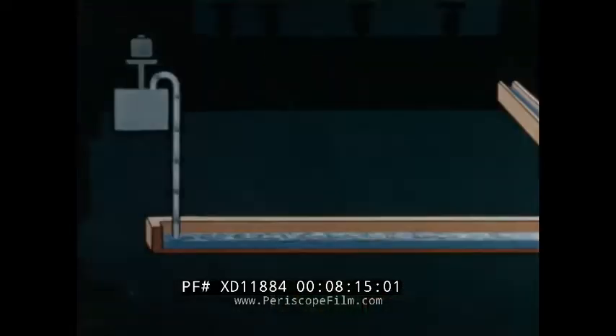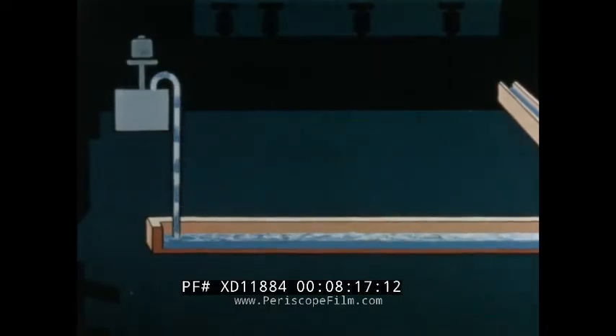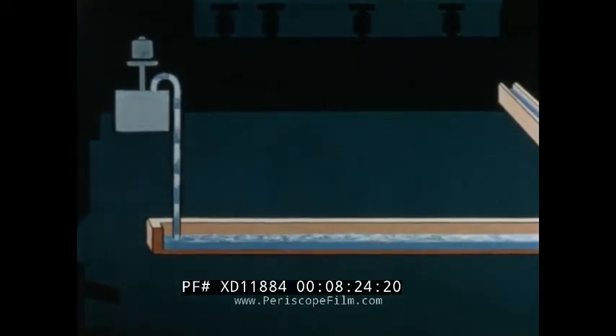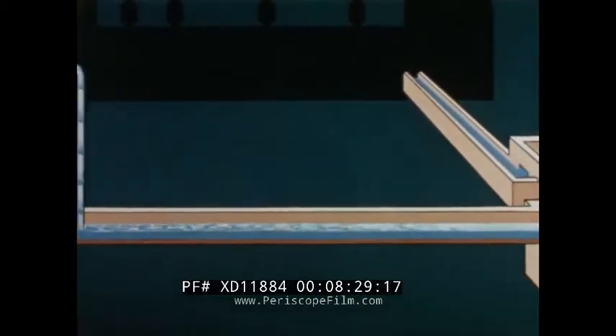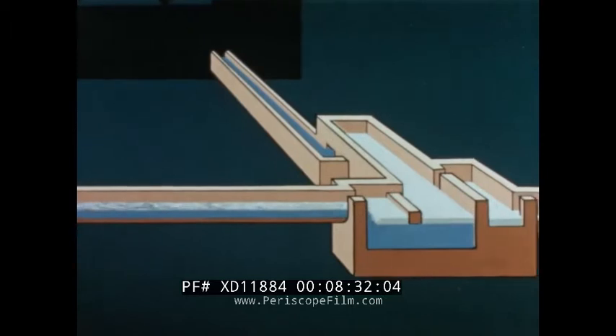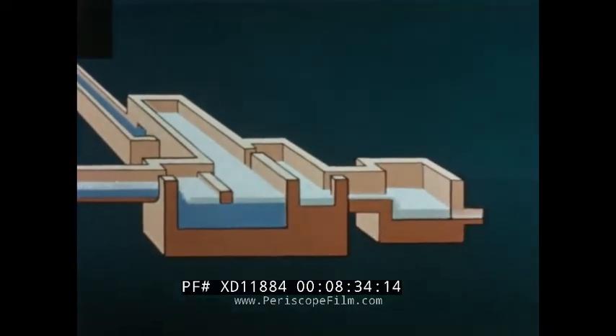Zinc not dissolved by the lead droplets and the furnace gases leave the condenser and pass to a water scrubbing system. There, the last traces of zinc and lead are recovered in the form of blue powder. The cleaned furnace gases are then available for preheating the coke and the air used in the process. Back in the condenser, the solution of molten zinc and lead is pumped into a water-cooled launder. The cooling separates the molten metals, and zinc, being the lighter of the two, floats on the surface of the lead. It's then a relatively simple matter to run off the molten zinc from the underlying lead.